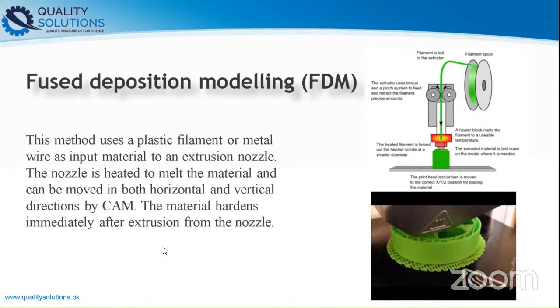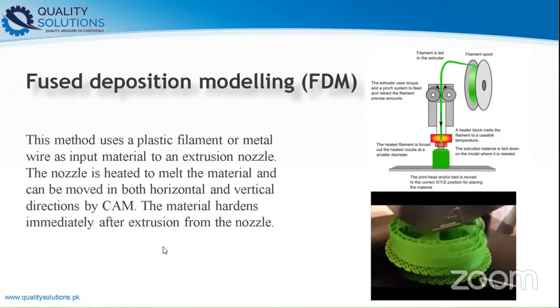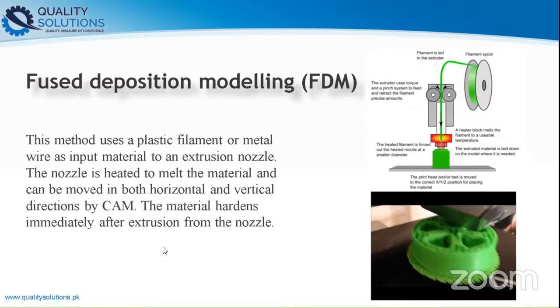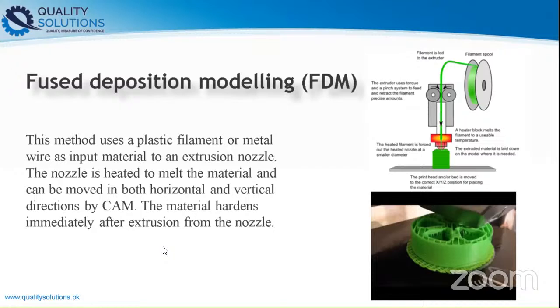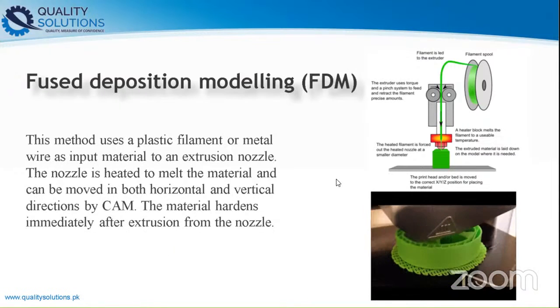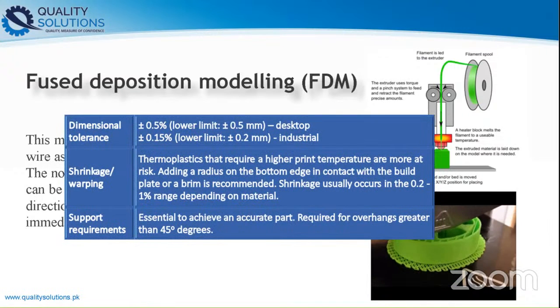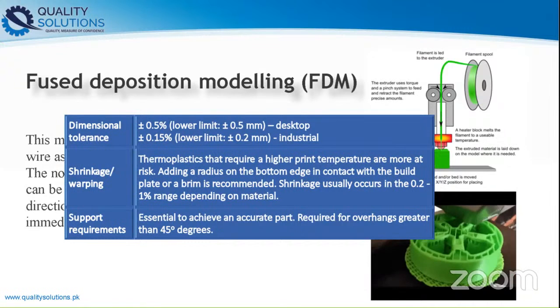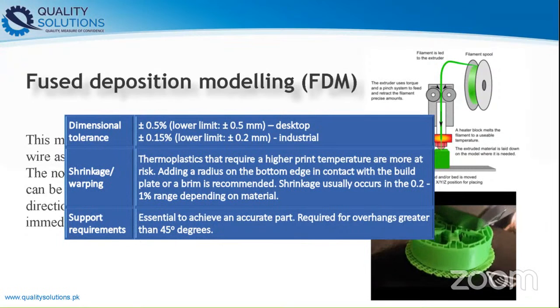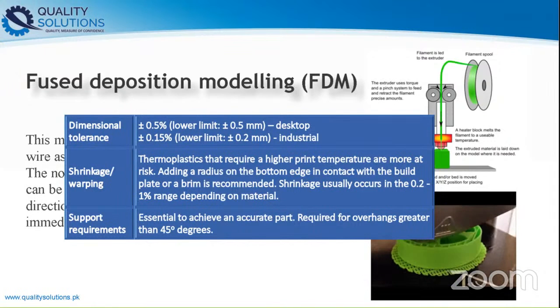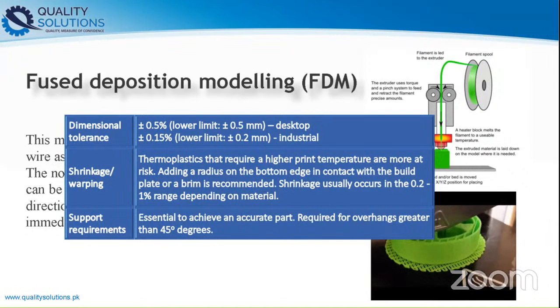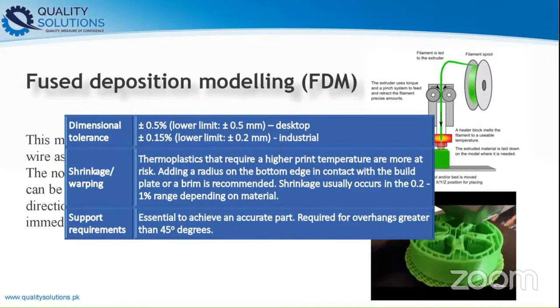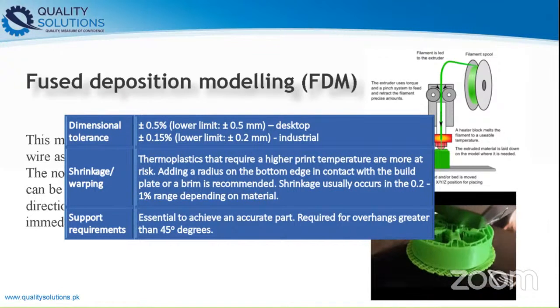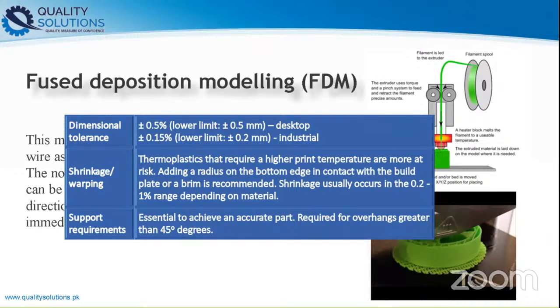Different materials are more prone to warping than others. For example, ABS is known to be more susceptible to warping than PLA. As we look at this chart, for both desktop and industrial 3D printers, thermoplastics require a higher printer temperature, which is more risky. Adding a radius on the bottom edge of the part in contact with the build plate is recommended. However, shrinkage usually occurs in the 0.2 to 1% range depending on material.